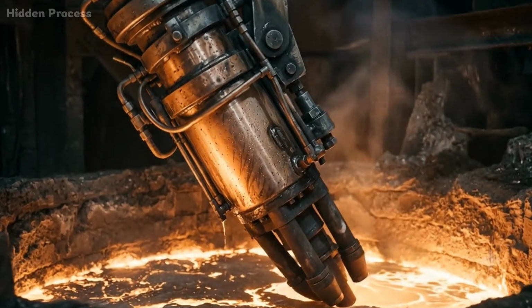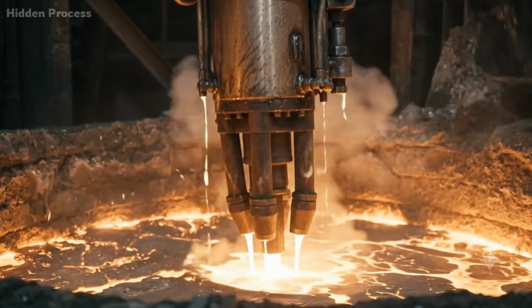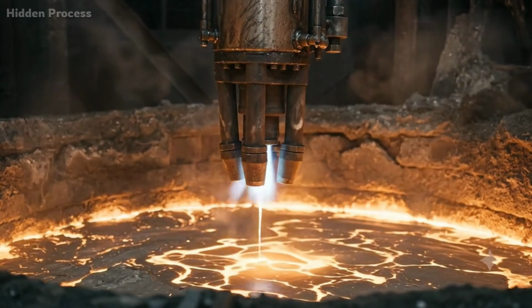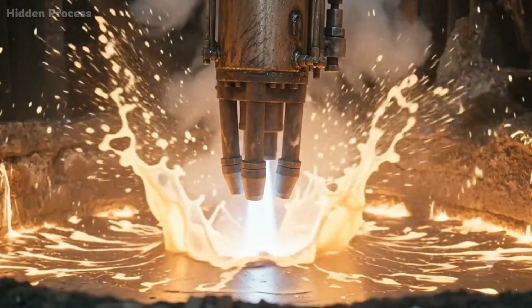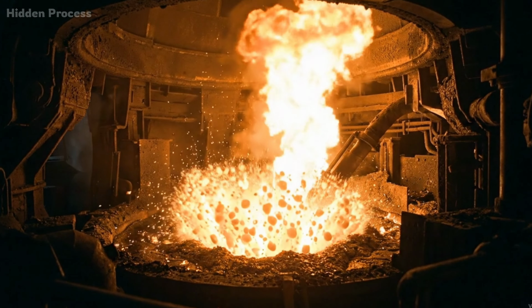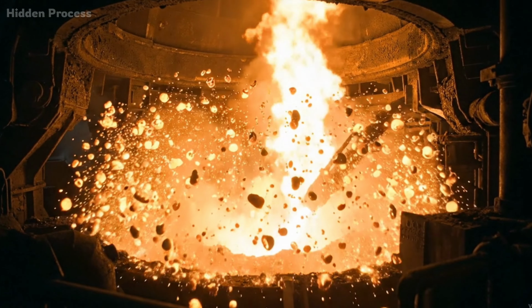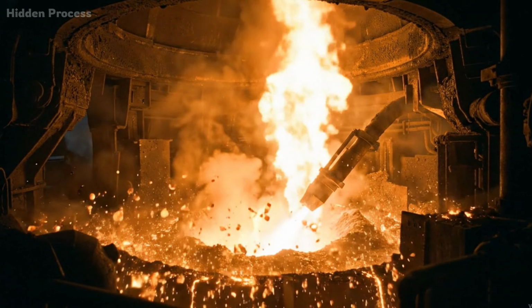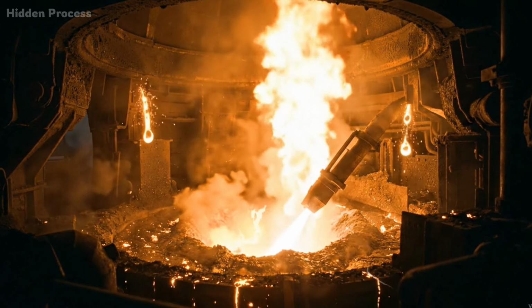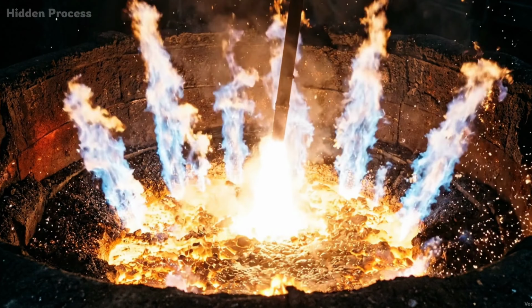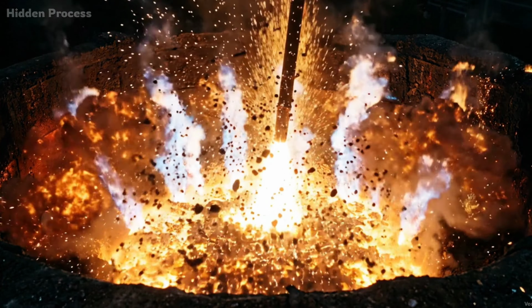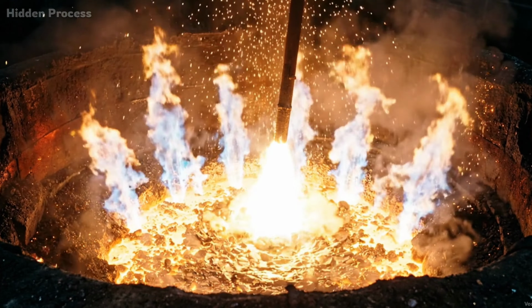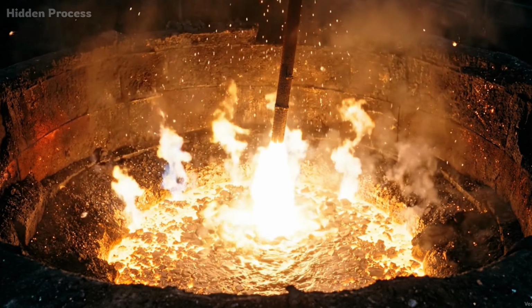Then a water-cooled lance drops from above, hovering just feet above the surface of the liquid metal. And it fires. Pure oxygen at supersonic speeds blasts into the molten iron. The reaction is violent. The furnace glows, flames shoot up, the temperature inside spikes. Carbon burns off as carbon dioxide gas, impurities oxidize and rise to the surface.